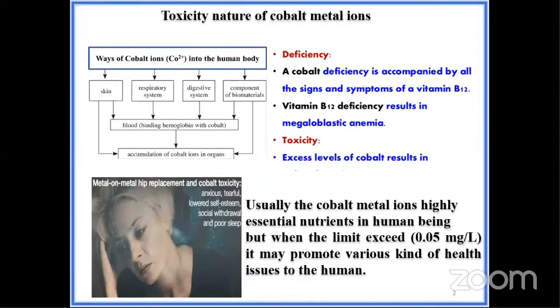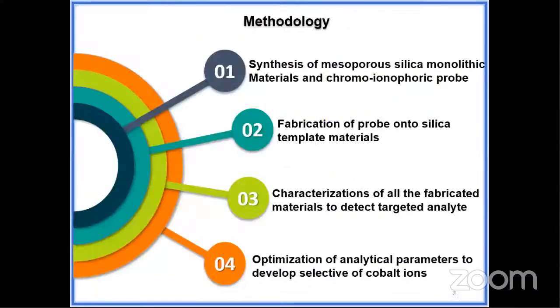So we have developed a solid-state colorimetric sensor to detect cobalt metal ions. These are the major methodology steps involved in our work. First, we prepared mesoporous silica monolithic material and a chromoionophoric probe. Then we fabricated the probe onto the silica monolithic template. After fabrication, we investigated the properties before and after fabrication of the probe onto the monolithic material. Finally, we optimized all the analytical parameters to develop a cobalt sensor.